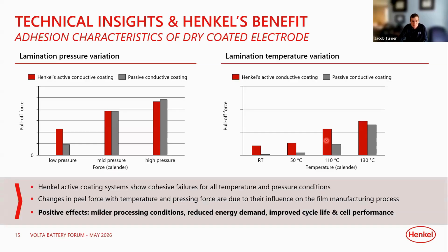So a couple key points here. The part that's not captured here is those red bars are all cohesive failures. So that's what we target in terms of our adhesive strength in this system. Typically, those freestanding films are not all that cohesively strong themselves. So we always want the failure mode to be those active materials just being ripped in half. We want to maintain adhesion to the foil and that active material and allow that failure mode to be the cohesive failure of the active material. And that's the maximum level of adhesion that we're able to get. So across all of those temperature ranges, we're seeing that. You do see some change, as those conditions do impact the cohesive strength of those films themselves. So this active system enables this technology, allows for milder processing conditions and improved cell performance.